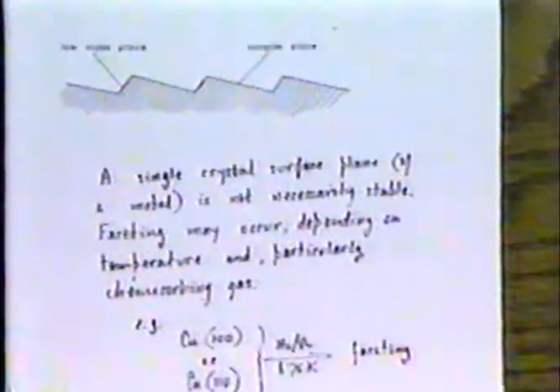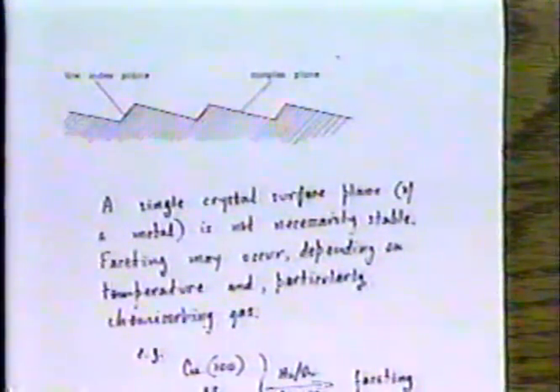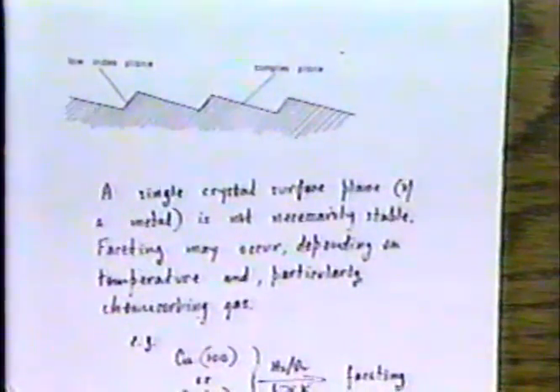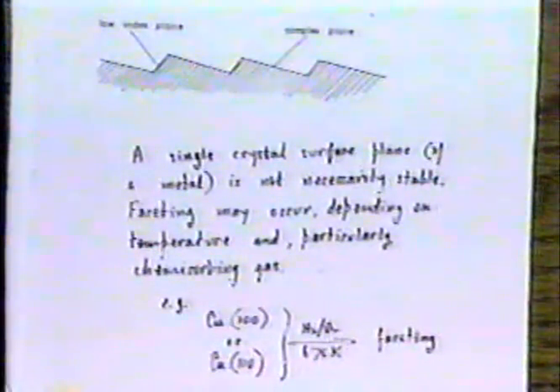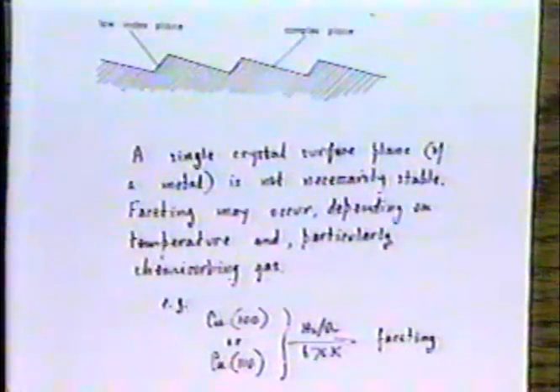Page 11 says something about this. If one takes a single crystal surface, that is a flat surface, with the average surface being flat, and treats it particularly in an oxidizing atmosphere, the surface may rearrange and break up into something which diagrammatically can be represented here as a mixture of a complex plane, that is a high index plane, and a low index plane.